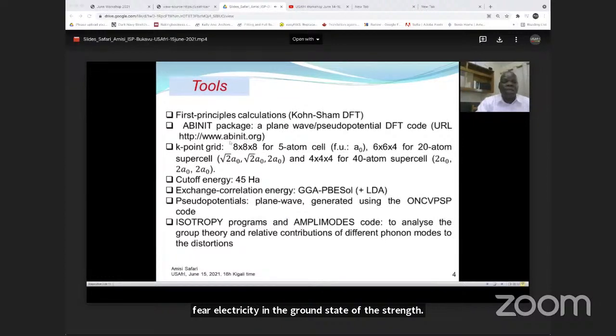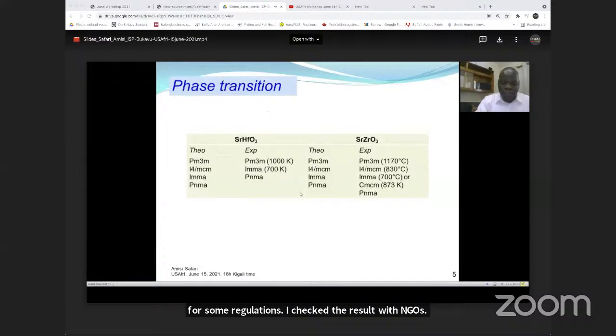Here are my tools. I use the ABINIT code, and for exchange correlation energy, I use GGA PBEsol. But for some calculations, I checked the result with LDA also. Here are the different phase transitions of these two materials. You can see that indeed the two compounds present the same phase transition, even if in strontium zirconium some studies put the Cmcm phase in place of the Pnma phase. In our case, our study has shown that it is the Pnma phase that is energetically more stable than the Cmcm phase, but the ground state stays the same.